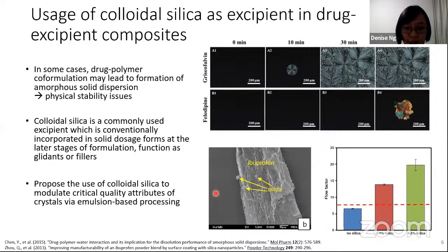So here what we have shown is that for a particle of ibuprofen, you can coat it with colloidal silica, and this results in a substantial improvement in the flow factor, which is a measure of the flowability of the powders. What we would like to do here is not to use colloidal silica to improve flowability, but to propose the use of colloidal silica to modulate critical quality attributes that we have mentioned earlier, such as the polymorphic form and crystal dimensions via emulsion-based processing.